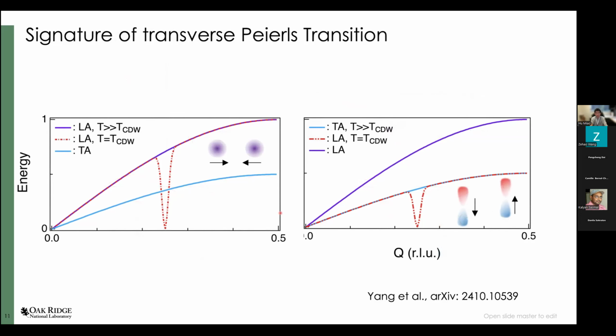As experimentalists, we always want to know how to distinguish a longitudinal Peierls transition from a transverse Peierls transition. Is there any physically measurable quantity that we can talk about? Here is how we distinguish longitudinal from transverse. On the left, I show the Kohn anomaly that only appears on the longitudinal acoustic phonons, and consequently you will have a longitudinal Peierls transition. But for the transverse Peierls transition, you would expect the longitudinal phonon doesn't show much change as you cool down. Instead, the transverse acoustic phonon should show a Kohn anomaly, and the transverse acoustic phonon will condense, giving you the transverse Peierls transition.